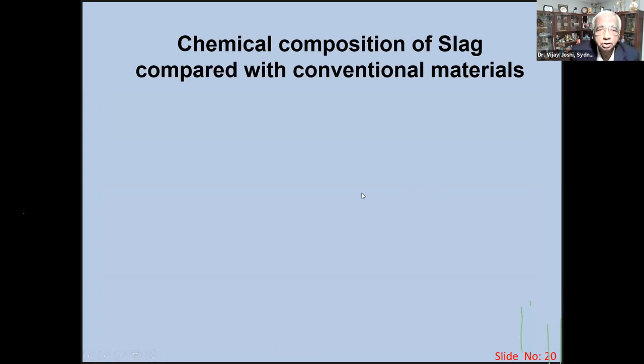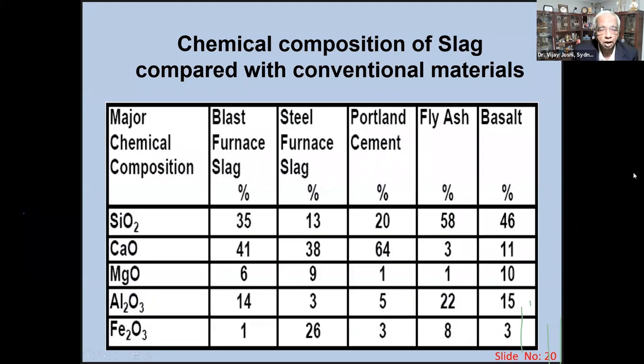Now, as you know, whatever we are using as a new product, generally new products are used against the conventional material. And all the physical properties are based on the chemical composition. So what I did is, I have compared the chemical composition of two critical slags. You see that all these are oxides: SiO2, CaO, MgO, Al2O3.